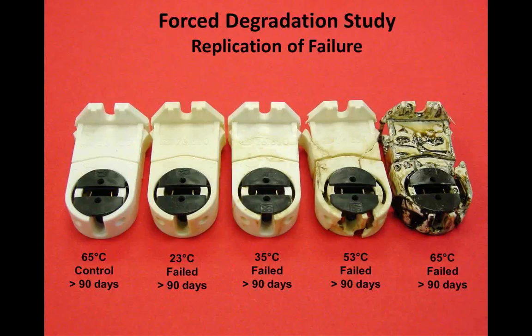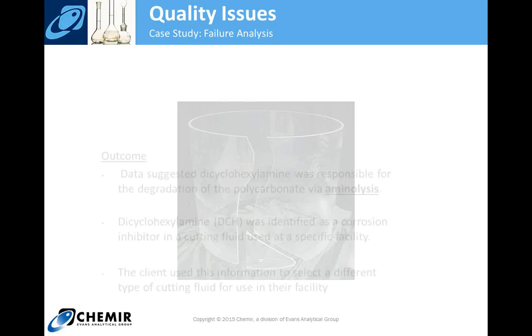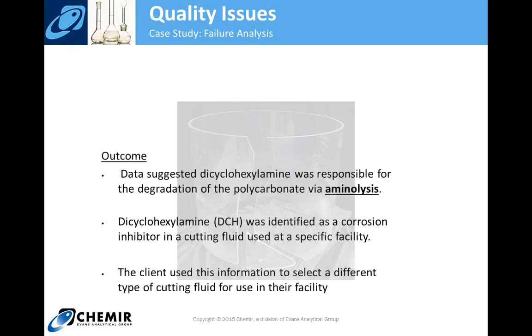But now the question is, where is DCH coming from? And if you remember, I mentioned earlier, this failure was only at a single client of our client, a single large facility where this failure was occurring. So what is DCH? Where did it come from? Well, the conclusion from all this is that the dicyclohexylamine was responsible for the degradation of the polycarbonate. We seem to prove that conclusively.